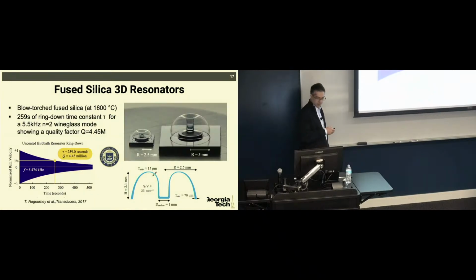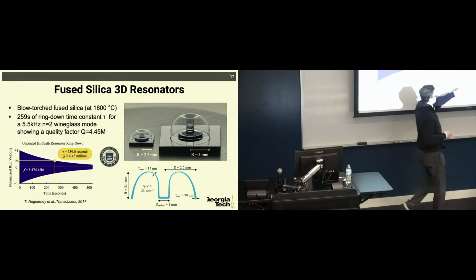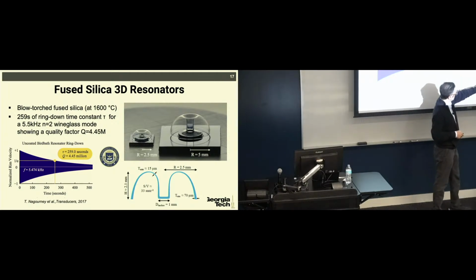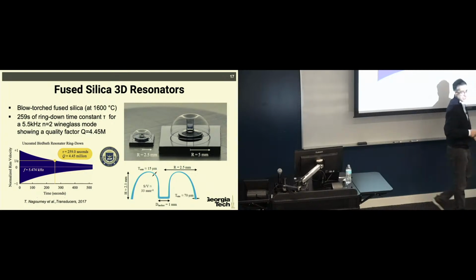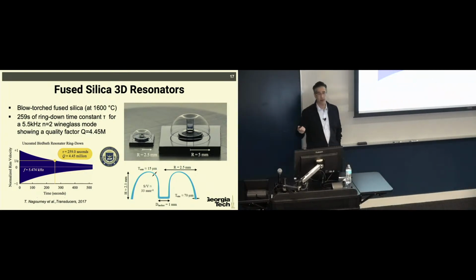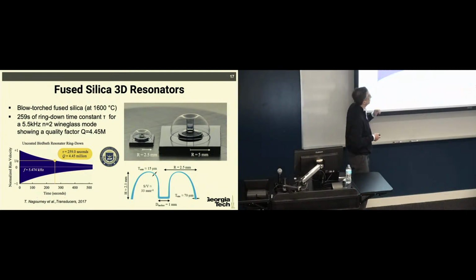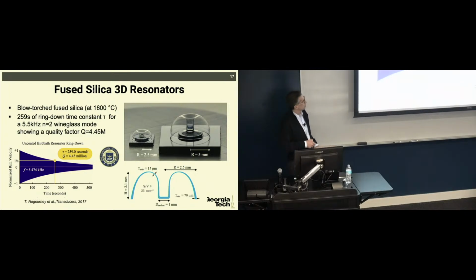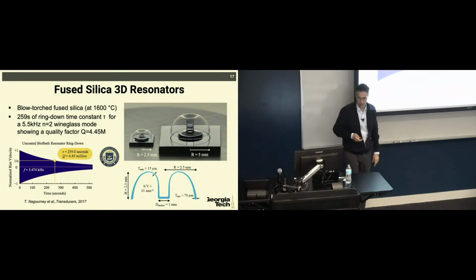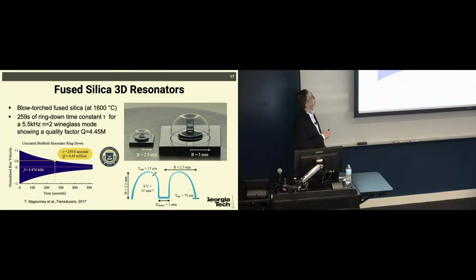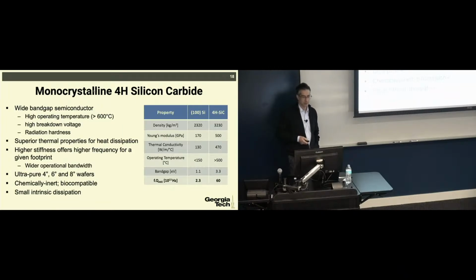Later on, University of Michigan showed that if you work with these 3D resonators and use thicknesses that are much thicker than what we use, we use 1 micron thickness, they use 70 micron thickness at the very edges, they were able to get to Qs at a much higher value, about 4.4 million at 5 kilohertz. So this is still to this date, I think, one of the record-breaking Q factors for low frequency devices. But what you see here is that this device is also very thick. It's about 6 to 10 millimeters thick. So planar integration is not going to be an easy job with this type of devices. And in case you wonder how this was made, it was made through a blowtorching process of a fused silica wafer. The fused silica was melted to create this form. Pretty cool process, but it's really not something you can use in high volume.